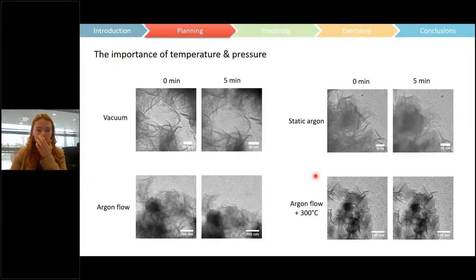And so we looked into this a bit further. When I was actually running my gas cell experiments with my sample that I mentioned before, I did quite a lot of stability tests. I tested it under vacuum, but vacuum here refers to 4 millibar of argon because it's actually in the gas cell. I tested it under argon flow at 1 bar. I tested it under static argon at 1 bar, and I tested it under argon flow at 300 degrees. It's not very clear from these images, but if you were to zoom in very close, you would see that all of these materials have been quite significantly damaged by the beam under all of these conditions, vacuum, argon, and argon flow, but not at 300 degrees, which again points to water.